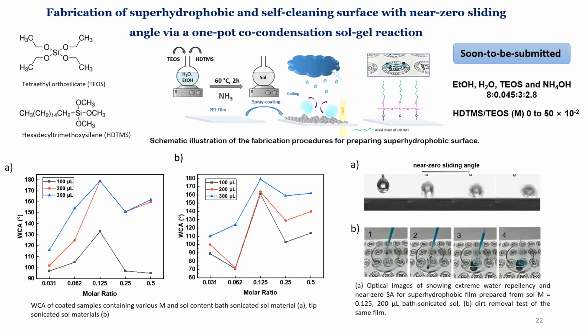Also, the cleaning properties were tested by putting some graphite on the coated surface with only a few drops of water. As you can see in the bottom image, it was easily cleaned.